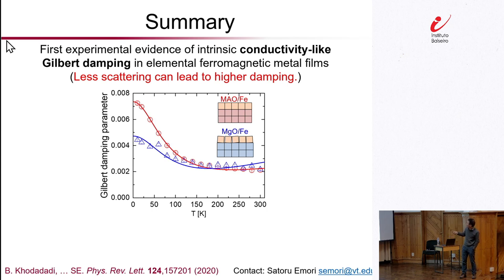So as a quick summary, what we have demonstrated is what we believe to be the first clear experimental evidence of intrinsic conductivity-like Gilbert damping in pure iron, or in an elemental ferromagnetic metal film.